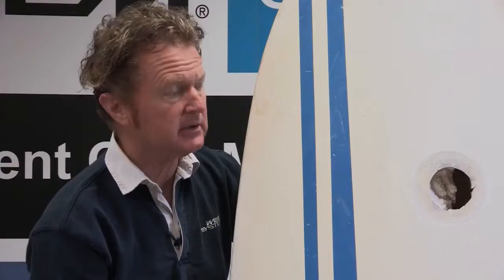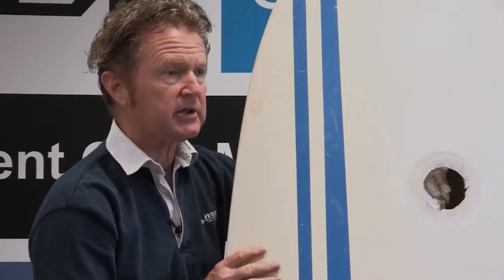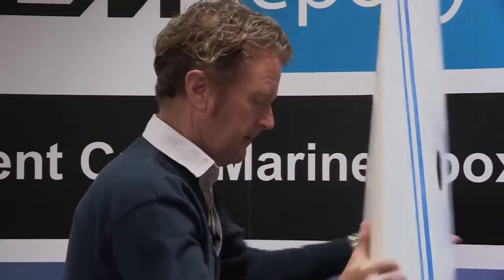Now to do that, we're going to put some release agent on a small part of the boat and create this backing plate using a single layer of glass fabric with peel ply on the back. Now, this particular topsides repair is in an area where there's not too much shape. Quite conveniently, I can do this on the other side of the hull because the shape is nice and symmetrical. So I'm going to mask an area off here and make my backing plate.